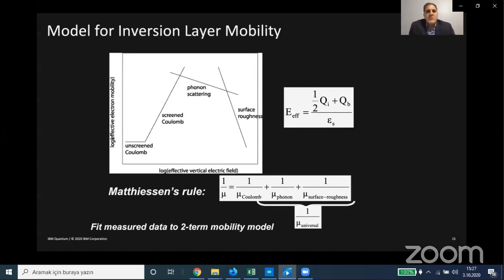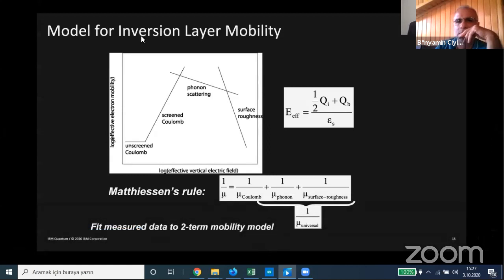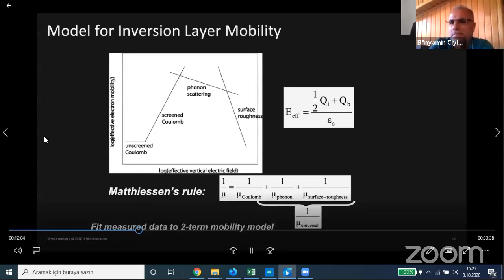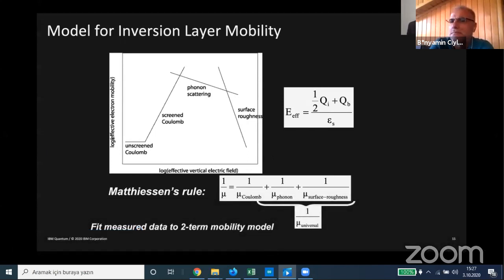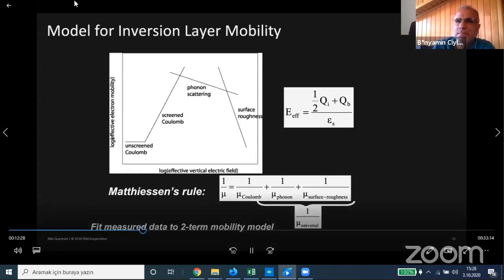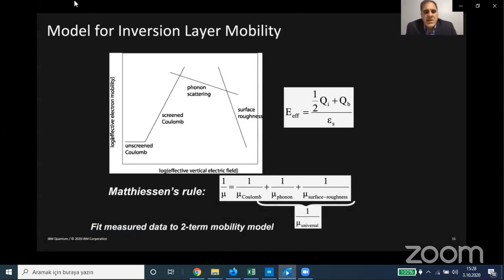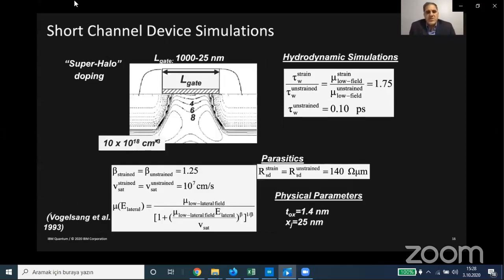As can be seen here, each component of scattering has a different dependence on the vertical electric field. Surface roughness scattering has a strong dependence, roughly a square dependence. On the other hand, phonon scattering has a weaker dependence, 1/3 exponent. The screened Coulomb mobility is the mechanism whereby, as one increases the gate voltage and increases the inversion layer electron charge, those electrons can screen the dopants, the ionized dopants in the channel, and hence reduce the Coulomb scattering. So that goes up with vertical field, and then you have an unscreened Coulomb mobility, which is flat with vertical field. So after fitting that model, a nanoscale MOSFET was simulated.